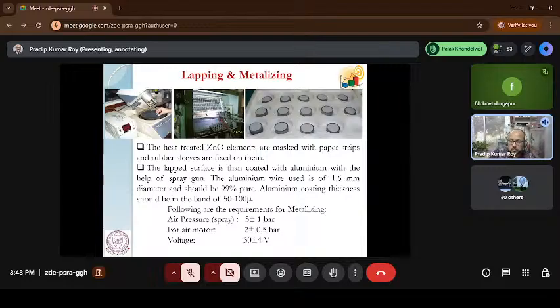After the glass coating, we do the lapping again. Lapping means we make both the surfaces parallel. Then after that, we do the metallizing. Metallizing means we spray aluminium metal through a method where initially the tip melts the aluminum. Then a pressure sprays that melted aluminum to coat it on the surface. It looks exactly like this kind of coated surface.